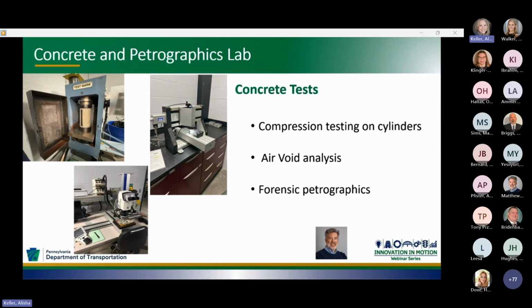Air void testing is done to evaluate the entrained and entrapped air void system in concrete to ensure there is adequate air voids to protect the concrete from freeze-thaw damage. Forensic analysis is usually performed on hardened concrete that is sent in from distressed pavements and structures. The concrete petrographers examine the concrete and determine the cause of failures, such as ASR, sulfate attack, carbonation, and poor mix design or curing processes.